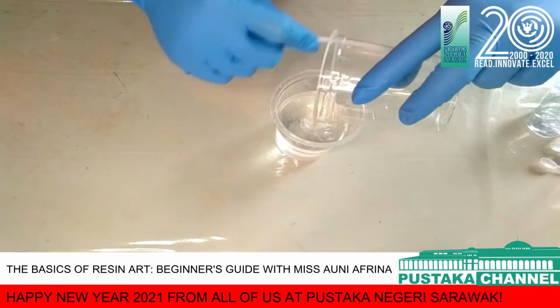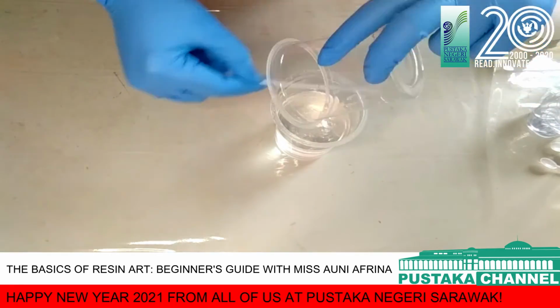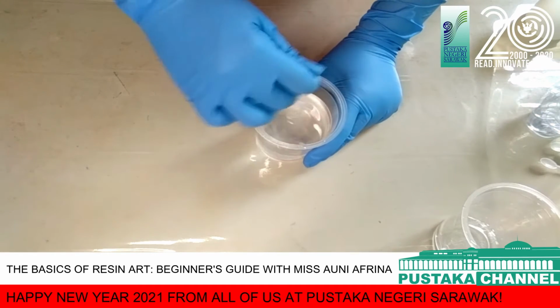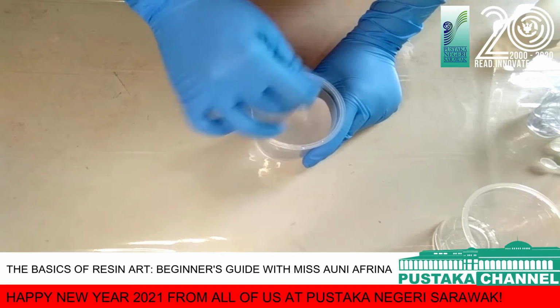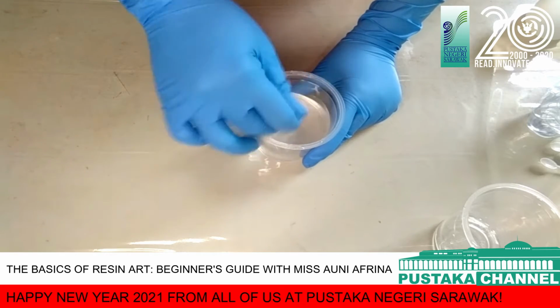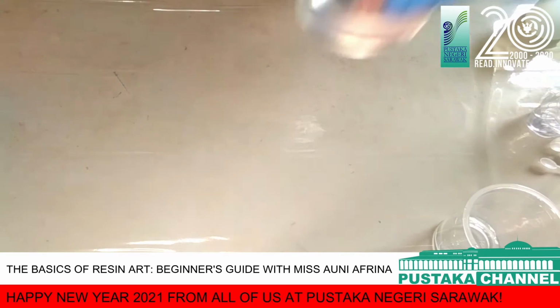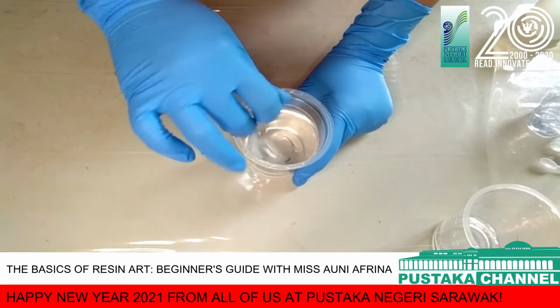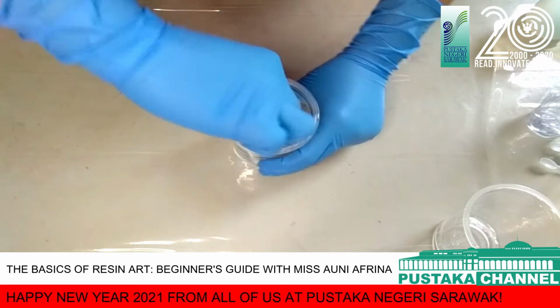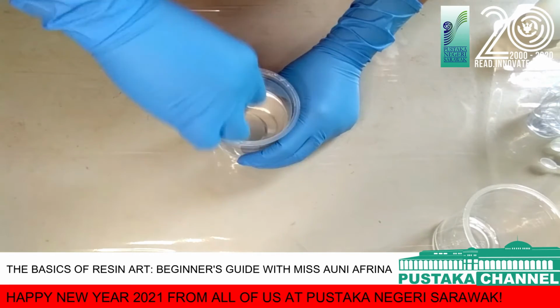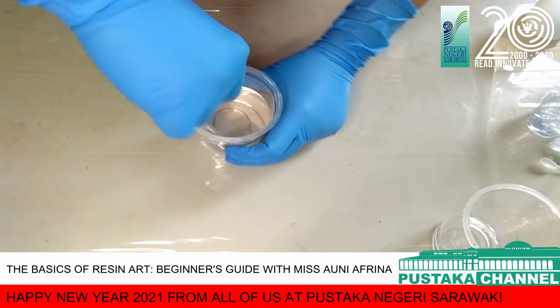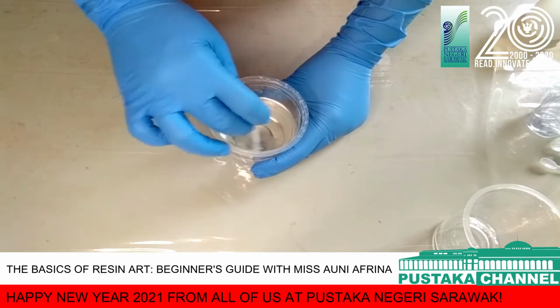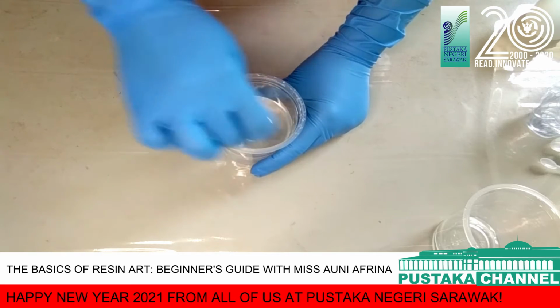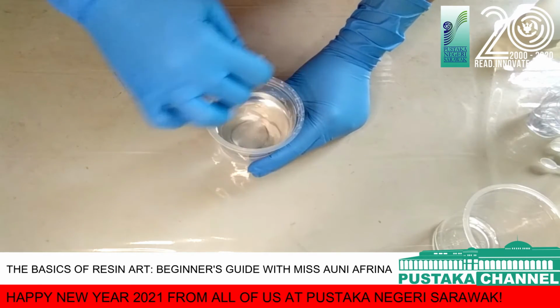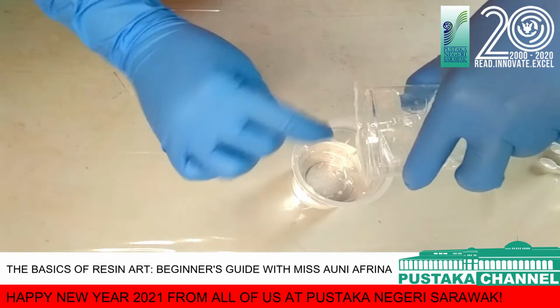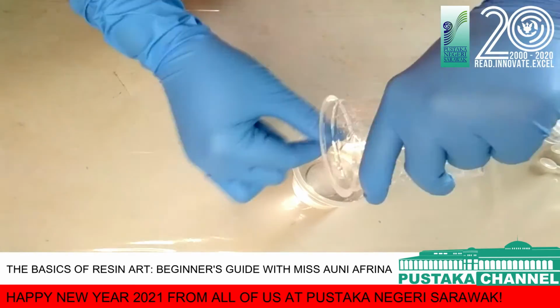Next, I mix them up in one cup and mix for about 5 minutes. For a smaller volume like this, 4 to 5 minutes of mixing should be enough. But if you're working with bigger volumes, mix them up for a little bit longer. Be sure to mix them up slowly to reduce the amount of air bubbles. I pour them into the other cup and mix for about 4 minutes.